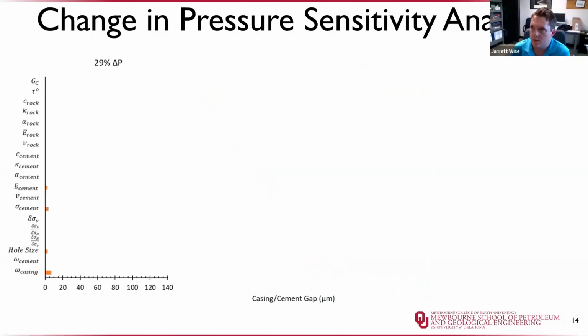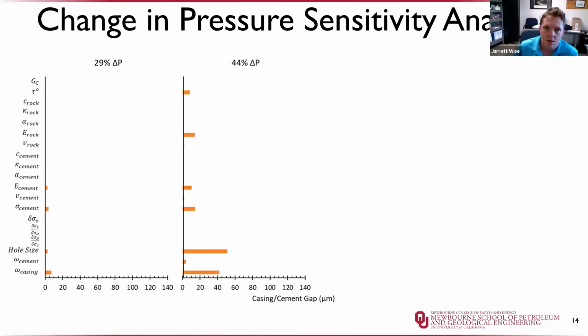So then once we got the microannuli due to pressure, we decided to do a sensitivity analysis to see what parameters in the wellbore are really predominant in causing microannuli to form. So first we chose a 29% reduction in pressure, which, as you saw from the previous slide, we didn't have any microannuli yet. So this should result in 0. But we see that just changing the cement Young's modulus, the setting stress in the cement, the hole size, and the casing thickness, we can actually start to get microannuli to form, whereas none of it was forming at this pressure.